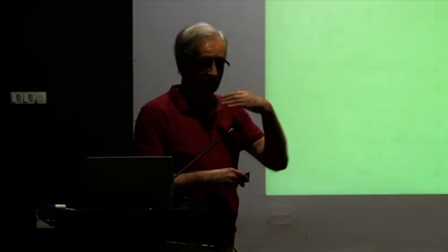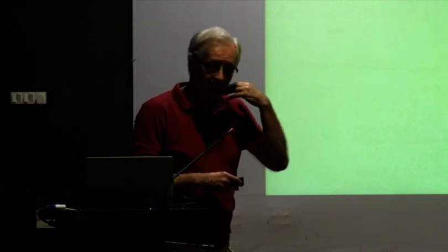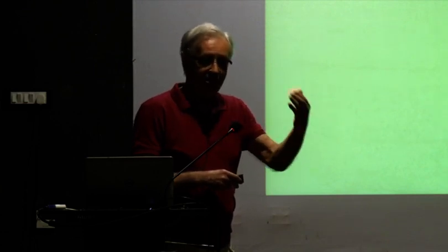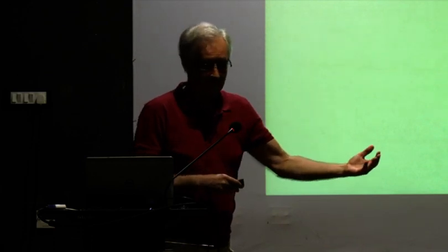And then you cool this in a magnetic field all the way to 5 Kelvin, and 8 Tesla. And you see some peaks associated with the martensite state coming up, but this 220 is not lost. It's still there, when you've cooled it in a very high field. So cooling it in a very high field maintains the austenite state all the way down to low temperatures.